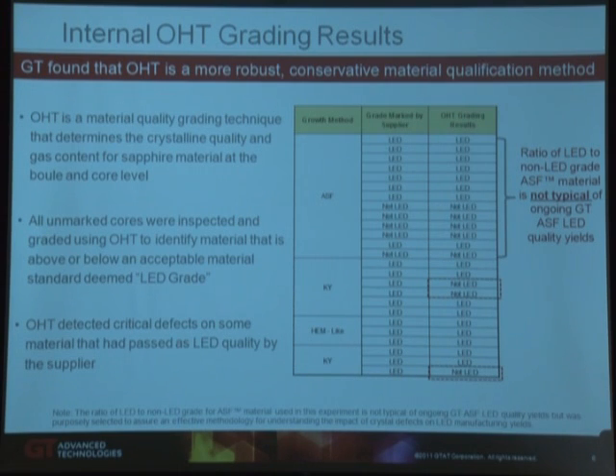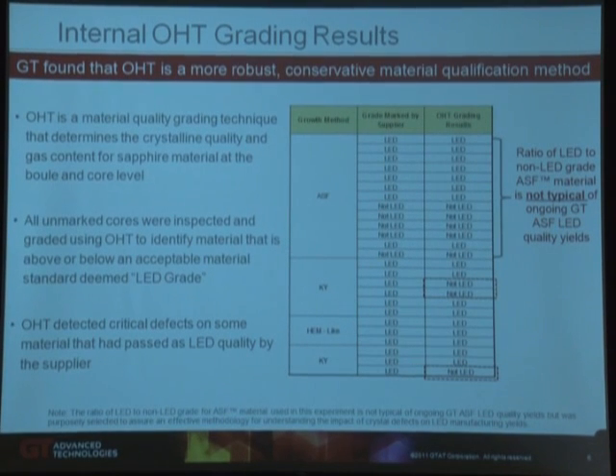OHT is a material quality grading technique that determines the crystalline quality and gas content, or bubbles, for sapphire material at the boule, the original material level, and at the core level. All of the unmarked cores, all 25 of them, were inspected and graded by our certified technician using the OHT to identify material that is above or below GT's acceptable material standard deemed LED grade.